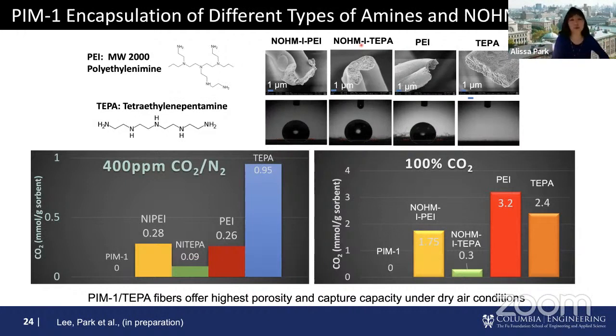We did test between direct air capture systems as well as 100% CO2, just looking at the CO2 capture capacity. And if you look at the left-hand side, it's very interesting that the NOHM-I-PEI case and PEI case work very competitively. But PEI, remember I was showing you that PEI is not thermally stable over multiple cycles. So this shows that NOHM-I-PEI-based electrospun fiber, this fiber encapsulated system, has really great potential for direct air capture.